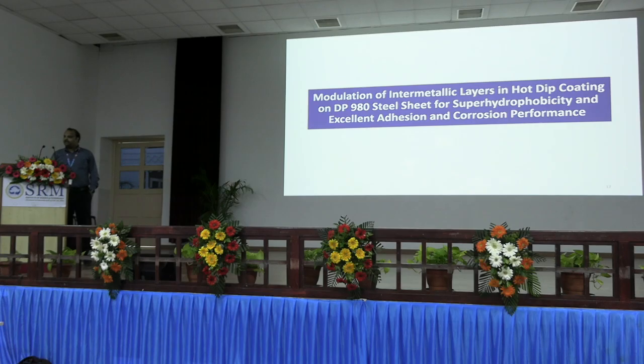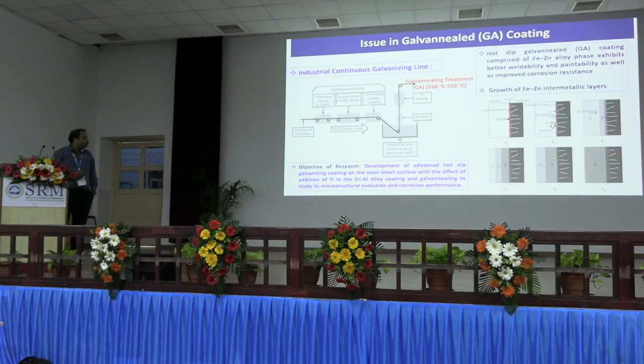So in the second technology, I am talking about the galva annealing coating. Just let me introduce that. After galvanizing, the galvanizing coating has very poor paintability and weldability. Therefore, after coming out, these galvanized coated steel sheets are further subjected to a post annealing treatment, which is called galva annealing.